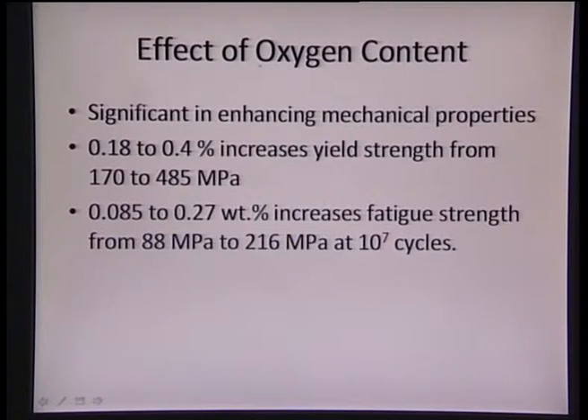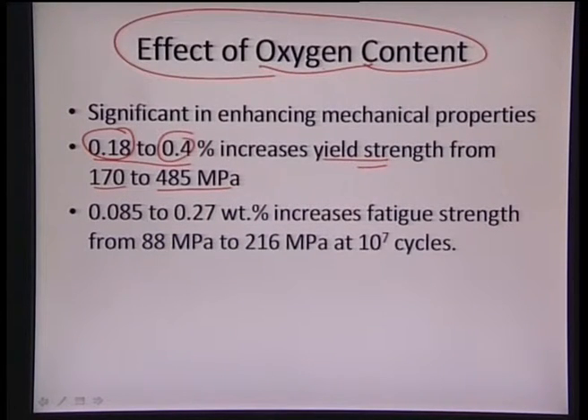And oxygen is also very predominant in terms of enhancing the mechanical properties. Like if we increase the oxygen content from 0.18 to 0.4%, the yield strength will increase dramatically from 170 to 485 MPa. So approximately more than 2.5 times improvement it can show in the yield strength just by doubling the oxygen content. So that is the approximate dependence on oxygen content in the interstitial. So once we have titanium, if we start inducing oxygen to a larger percentage, it will enhance the yield strength.